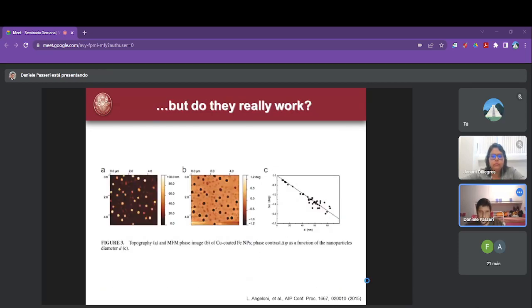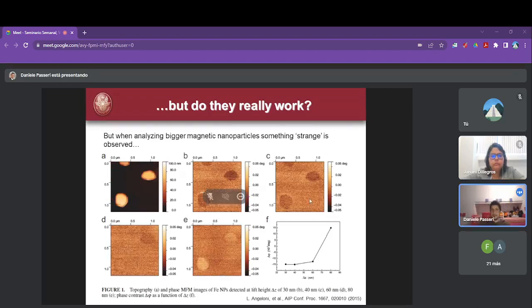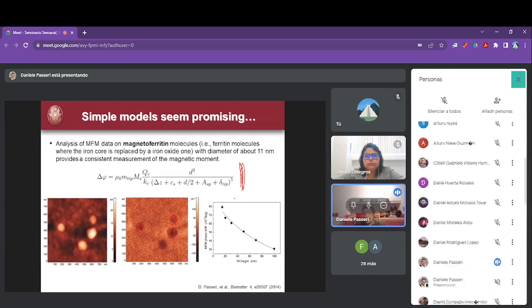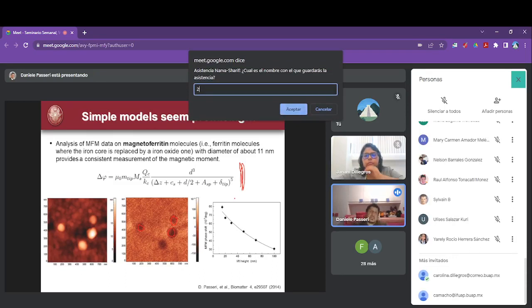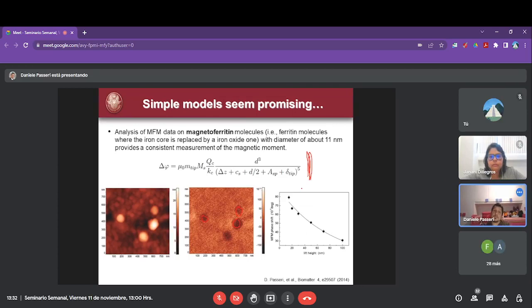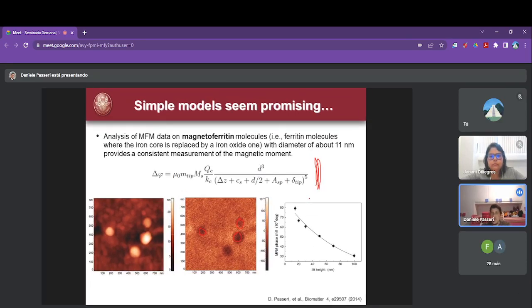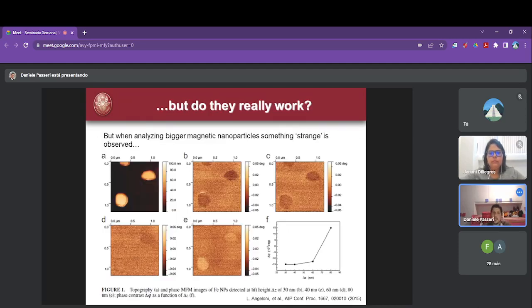But, oh, sorry. But these are very simple models. We have those very small nanoparticles. We are using a two magnetic dipole model. It seems to work very well, but we start to observe something strange. These are iron nanoparticles, the topography. You see, at low lift height, everything seems correct. Okay, I have dark nanoparticles, which means here there was a magnetic field, but these are details. In any case, there was an attraction between the tip and the nanoparticles.